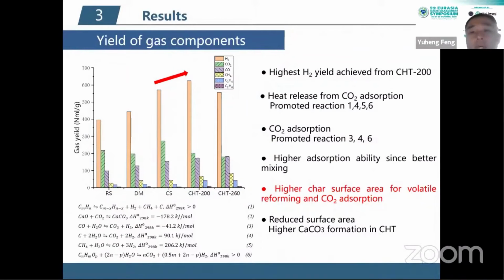From the view of gasification, we have volatile gasification with steam and gasification of the fixed carbon. In the sludge, the fixed carbon takes a very small proportion, only 5%, but the volatile content is as high as 40%. So it's very important for the volatile gasification on the surface.